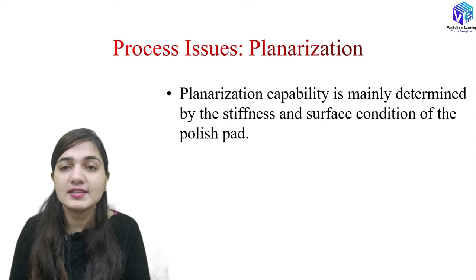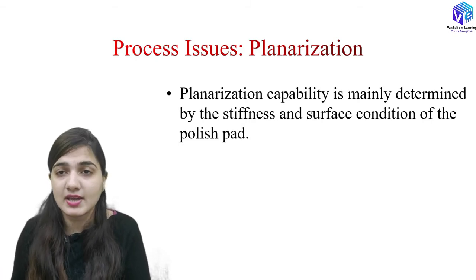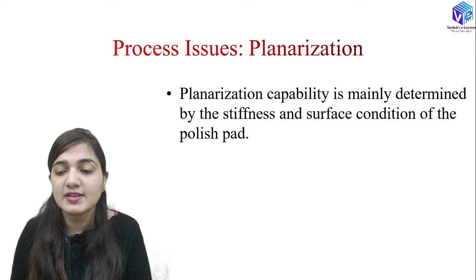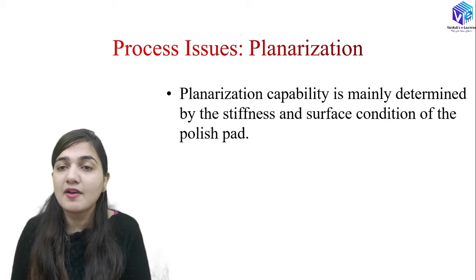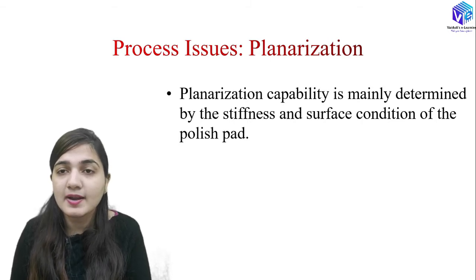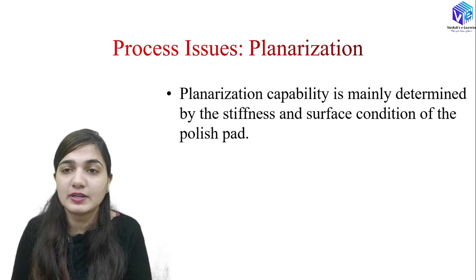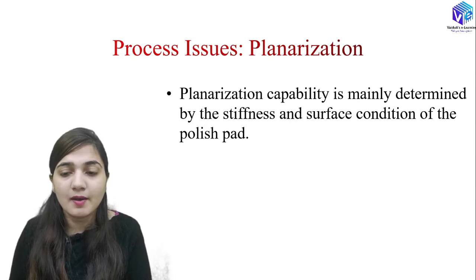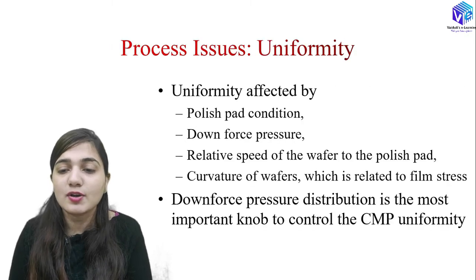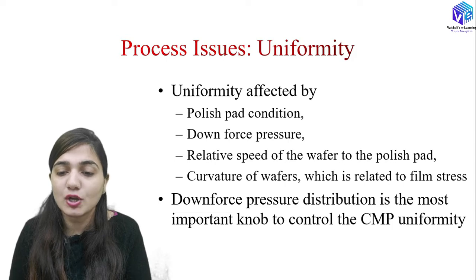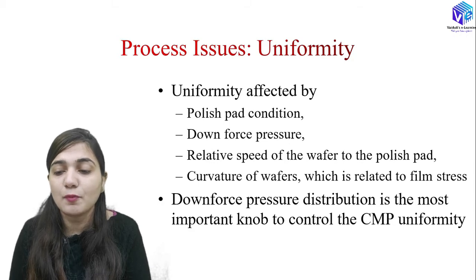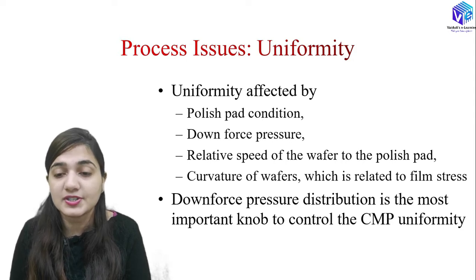Planarization is the capability that determines how planar my structure is and how much roughness has been removed. It is determined by the stiffness and surface condition of the polishing pad. If I have a thicker and harder polishing pad rotating at high speed, I will get the best planarization. Uniformity is affected by the polishing pad condition, downforce pressure, relative speed of the wafer to the polishing pad, and the curvature of the wafer, which is related to film stress.